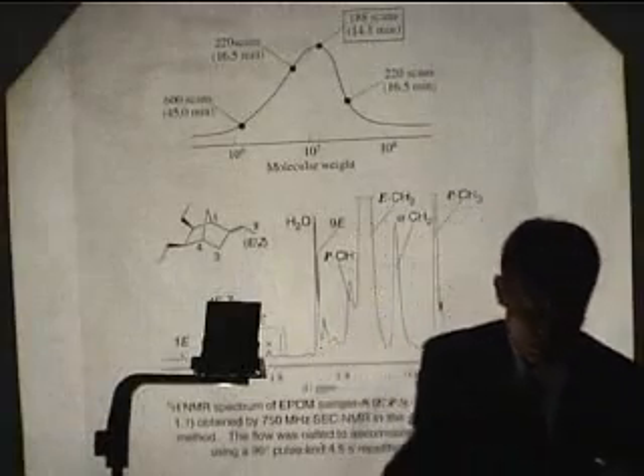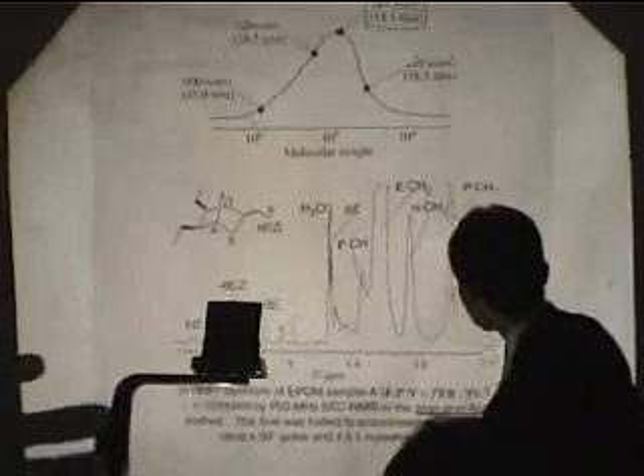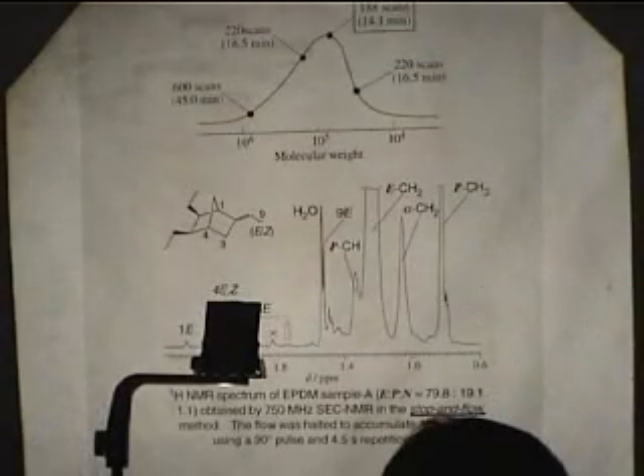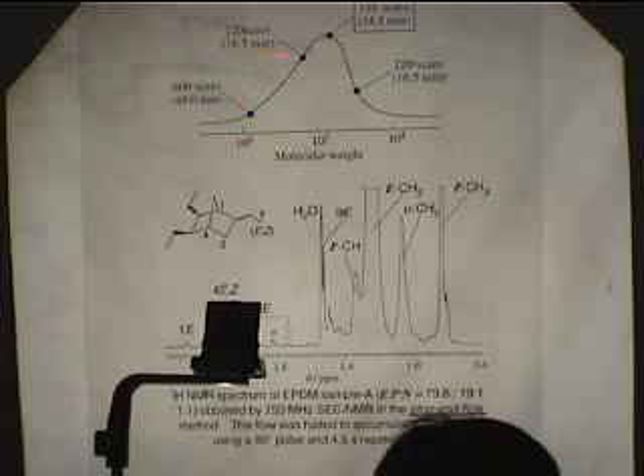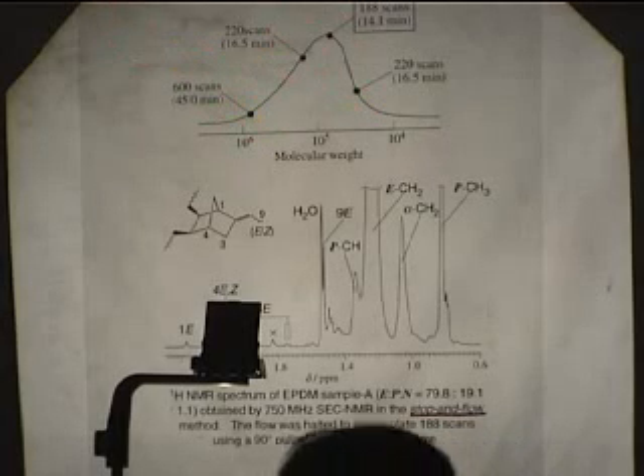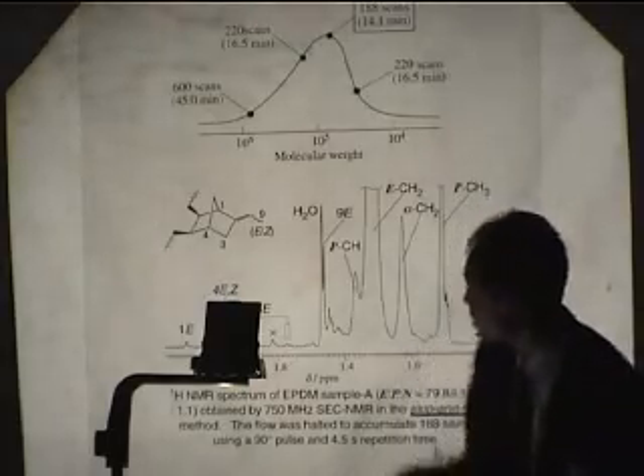we perform SEC-NMR under the stop-and-flow mode. In the stop-and-flow mode, the flow of the chromatography was stopped at these four points, and scans were accumulated to increase the intensity of the spectrum. By this technique, we can observe the diene signals.